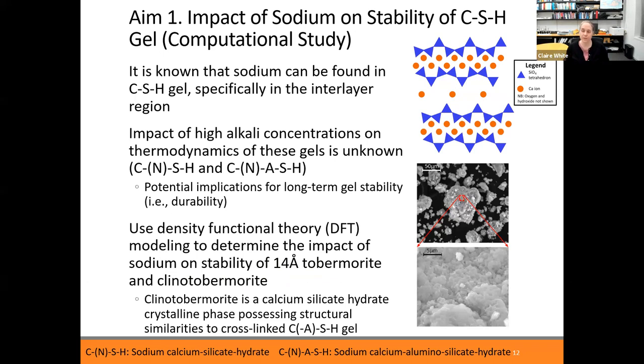And so that's why we're using crystalline analogs for what this disordered gel, the gel that we know is not a crystalline phase. So specifically here, we're using what's known as 14 angstrom tobermorite. And we've also used another one known as clinotobermorite. For 14 angstrom tobermorite, the structure is very similar to CSH gel, but these silicate chains are infinite in length. They're not chopped up like they are in the CSH gel. So that's the main difference between the two.